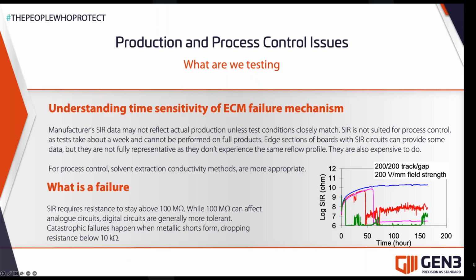So what does a failure look like? We'll talk about this a little bit later, but SIR requires resistance to stay above 100 megaohms. Whilst 100 megaohms can affect analog circuits, digital circuits are generally more tolerant, and catastrophic failures can happen when metallic shorts form, dropping resistance below 10 kilo ohms. On the right, we've got this graph showcasing the blue line as a normal test, no real issues. Then we've got examples of failures that have occurred with the pink and red lines, even the green line, and resistance has dropped, so you know there's an issue there. That's what an example failure would look like with SIR.